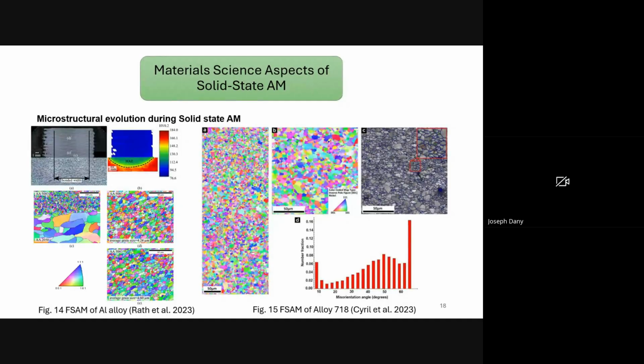The misorientation maps provide direct evidence for this mechanism. In the maps, the blue lines represent high angle grain boundaries, which is greater than 15 degrees. Green lines represent low angle grain boundaries, that is 5 to 15 degrees, and red lines represent subgrain boundaries, that is 2 to 5 degrees. In the deposit, the majority of the boundaries are clearly high angle, while low angle and subgrain boundaries appear only in small fraction. This dominance of high angle grain boundaries, along with the scarcity of subgrains, aligns perfectly with the discontinuous dynamic recrystallization mechanism expected for alloy 718. The limited presence of subgrains is mainly because the low stacking fault energy hinders dislocation recovery and subgrain rotation, making continuous dynamic recrystallization almost negligible.